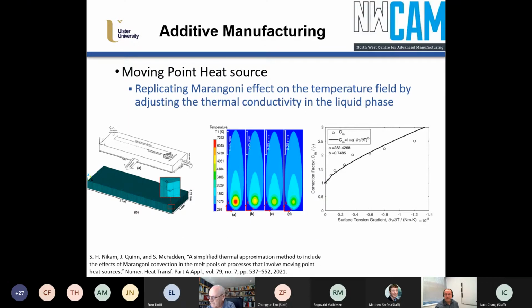Very briefly then, moving point heat sources. Modeling in ANSYS and Fluent, we are looking at the effect of Marangoni convection on the moving point heat source. There's a temperature gradient across the top surface of the melt pool in additive manufacturing, and this causes a surface tension gradient, and that sets up Marangoni convection. The effect of that Marangoni convection is to reduce the overall peak temperature. It broadens out the melt pool and makes it more shallow.